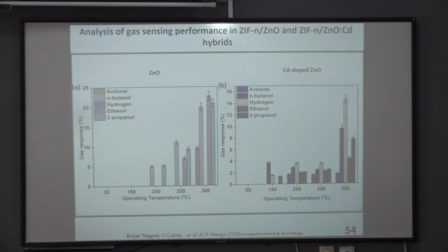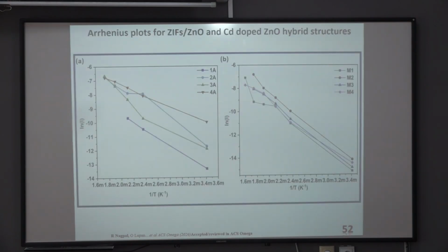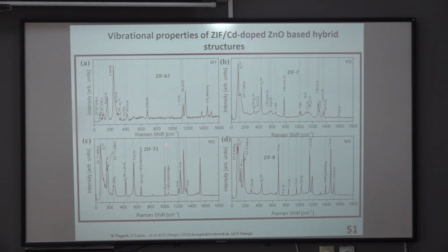So we can say that even though we used cadmium doping of around 0.2 atomic percent, it had immense impact on the gas sensing performance. Also, if we talk about the Raman peaks, even for 0.2 atomic percent of cadmium doping, there is a slight rightward shift of Raman peaks towards higher wave numbers, which could be attributed to the higher ionic radius of cadmium 2+ compared to the zinc 2+ sublattice, which will create lattice stress. That's why we observe this kind of change.